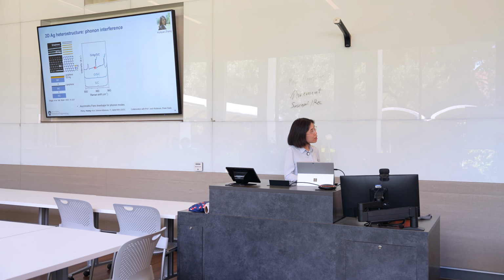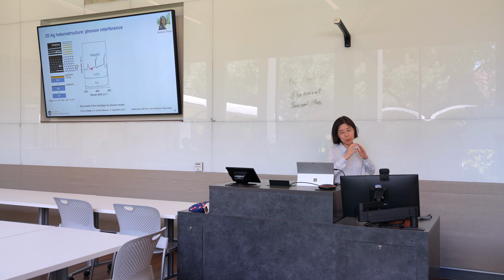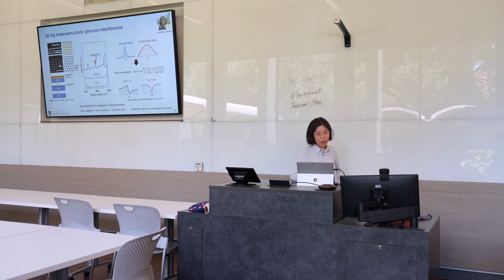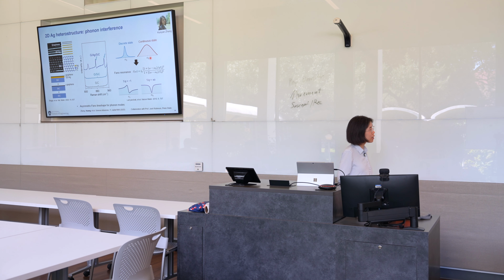And not only that, these modes do not have the conventional Raman mode shape or phonon mode shape. The conventional Raman modes have the symmetric Lorentzian line shape. But these apparently are not symmetric. They have the shape called Fano line shape. The Fano line shape is a result of the interference between a discrete state and a continuum state. The discrete state is basically the phonon modes. The continuum state can be several things. It can be electron excitation, defect phonons or phonon polaritons, and so on. So because of this interference, we have this Fano line shape.